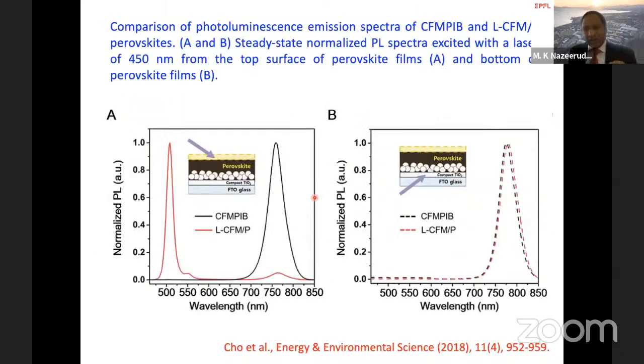The other way of characterizing these materials is shown here. So now we take two cells, one as the reference, that's a cesium, formamidinium, methylammonium, lead iodide, and bromide perovskite. That's a reference sample. We excite at 450 nanometers. From the top side, we see only one emission coming from the three-dimensional perovskite. However, if we deposit the two-dimensional perovskite on the top of three-dimensional perovskite, now we excite at 450 nanometers.